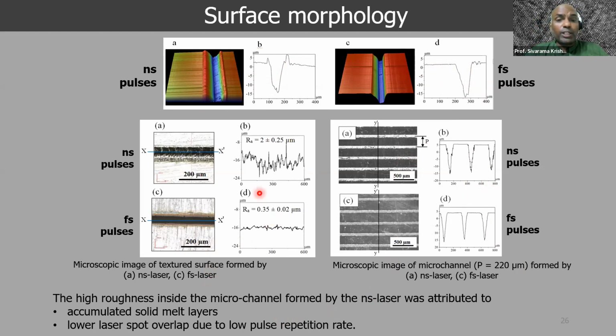And if one did surface roughness measurements, as we showcase in this left panel, the top row is nanosecond pulses, the bottom row is femtosecond pulses. You can see that the roughness within the grooves is also far smaller, almost a factor of 10 smaller, in the case of femtosecond pulses as compared to nanosecond pulses. So of course, we would expect that these would be tribologically more preferable.